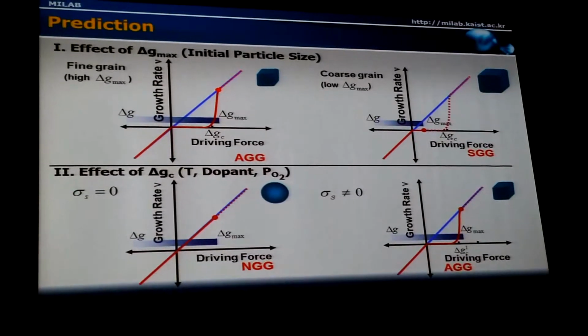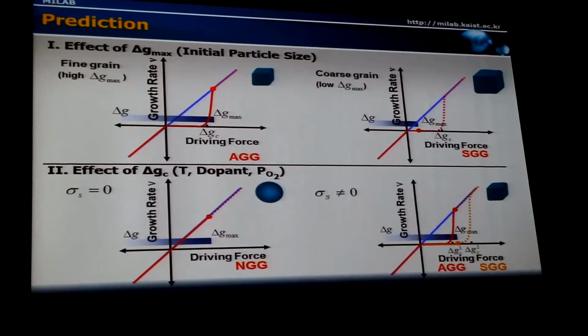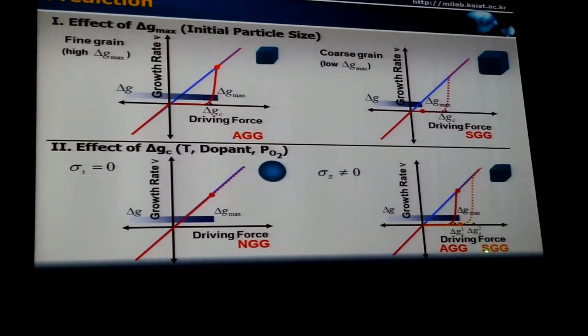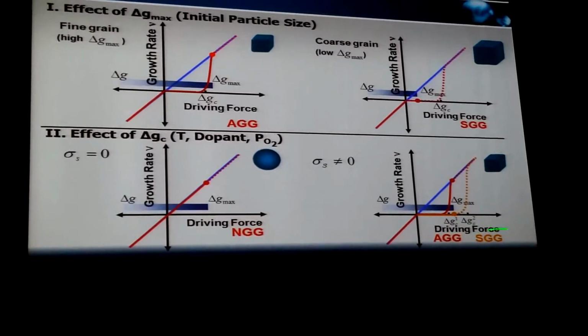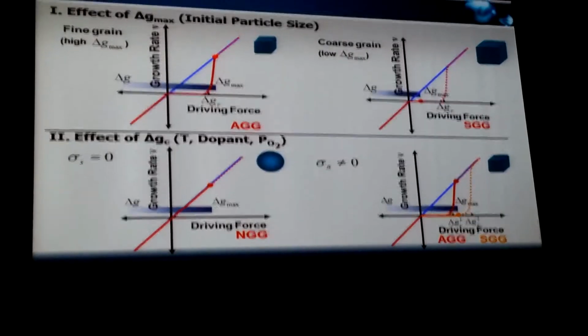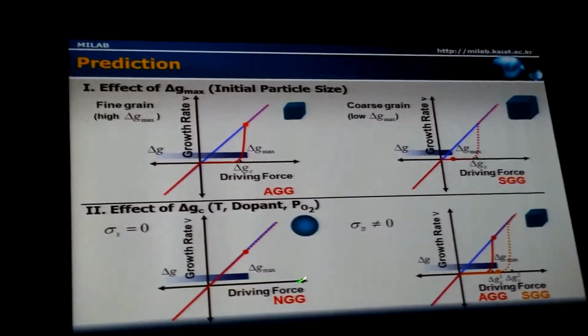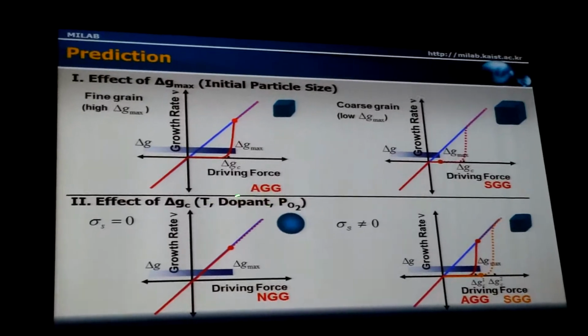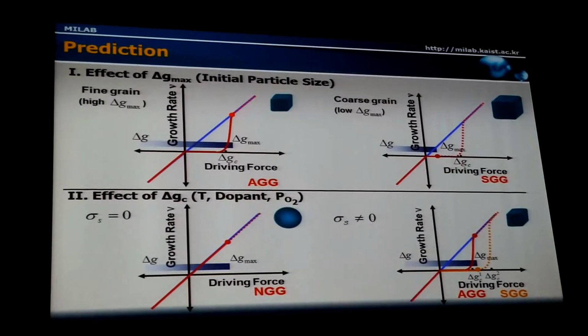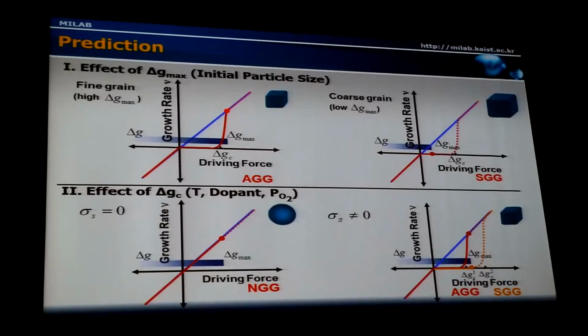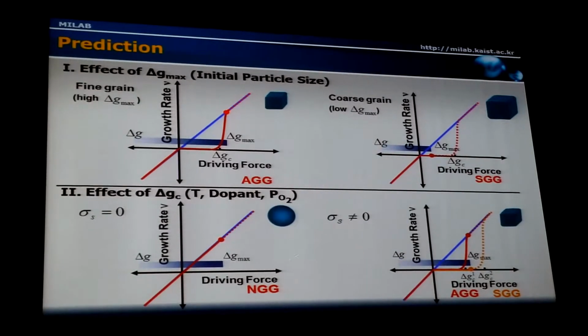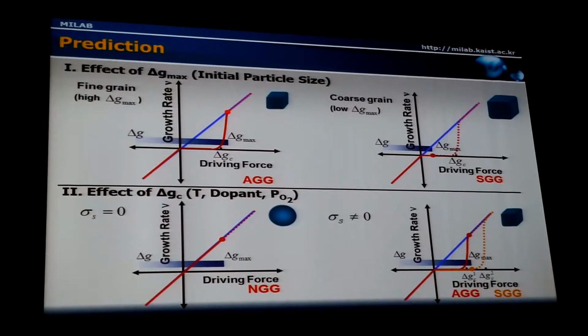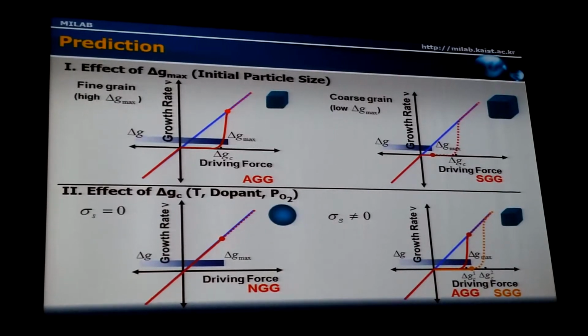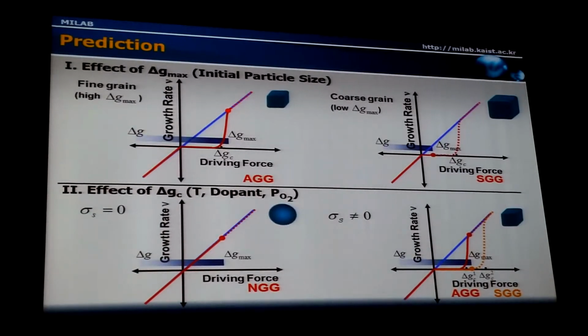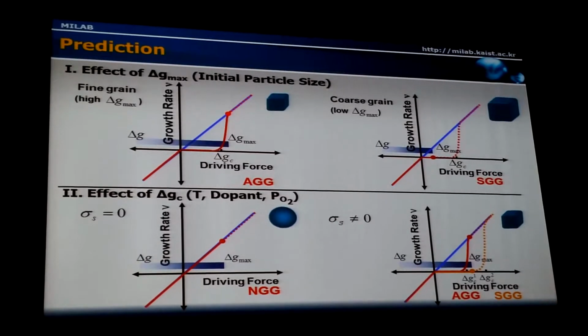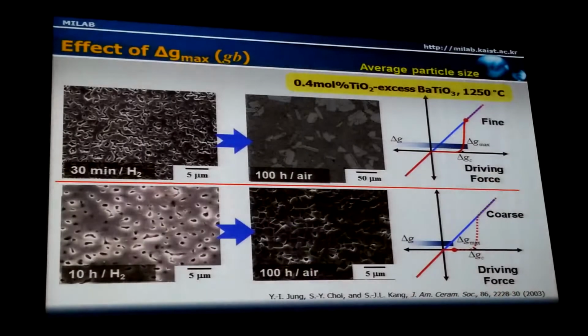If the critical driving force increases further, then none of the grains will grow appreciably, and stagnant grain growth will appear. So when you change the critical driving force by changing temperature, adding dopant, or changing oxygen partial pressure, we can expect to observe different types of grain growth behavior, for example, normal, abnormal, and stagnant. Let me now show you some examples that support these predictions.